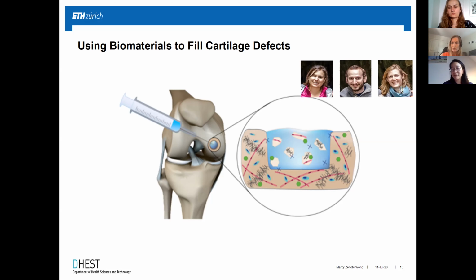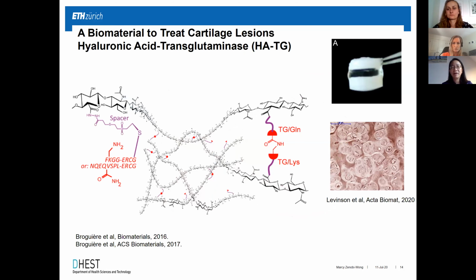And the important quality that this material needs to have is that as it's injected and begins to polymerize in the joint space, it's very important that it would also adhere to the joint space. So it needs to also have this adhesive property, so that the repair tissue is actually integrated into the joint and not just floating around where it wouldn't be functional. So these students worked quite hard to come up with a material that would fulfill all these different requirements. And this is a schematic of the material.